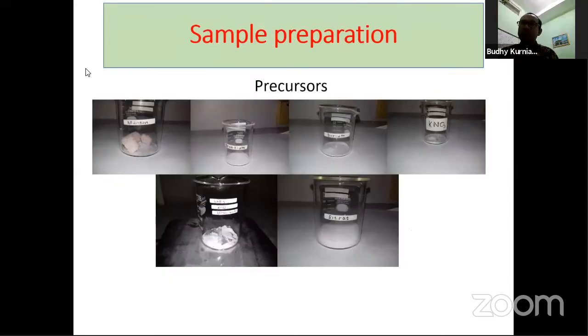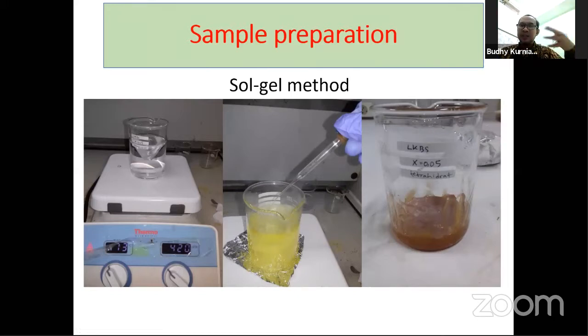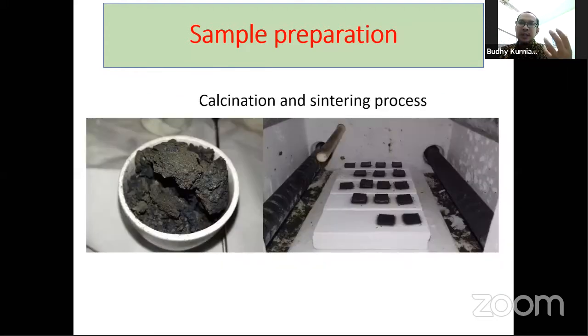Next, please. This is the sample preparation of our sample. We use the sol gel method. I just introduce it very briefly, since the time is very limited. Next, please. This is the precursor, and we use the sol gel method. We use some solutions to make a gel. After that, next, please. We make a calcination and sintering process after the sample is pelletized, to become a bulk material. Next, please.